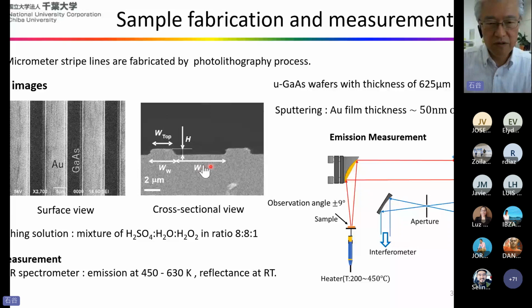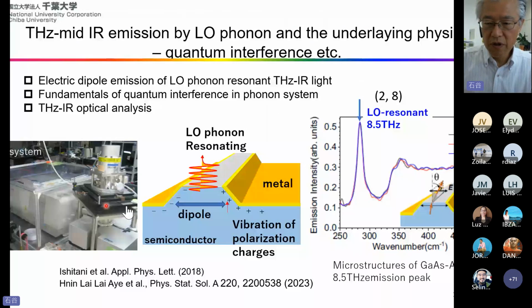This mesa structure is fabricated and the sample is attached on a heater, and the thermal radiation is monitored by the FTIR system. This is the system, and this is a result. By using gallium arsenide, with a gold film deposited partially on the surface, we have observed the LO phonon resonant emission at 8.5 terahertz. This is very important because it says that we can convert heat energy to electromagnetic energy, which can be used for communication.